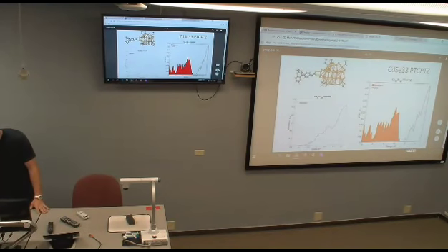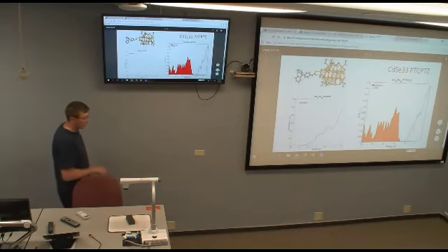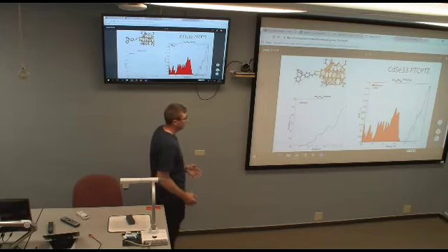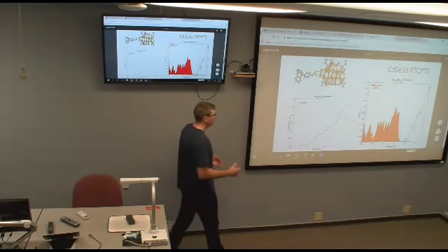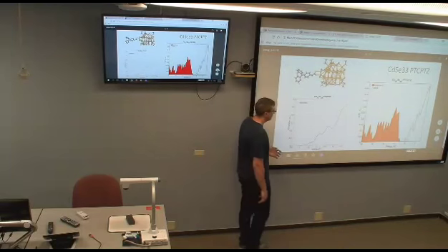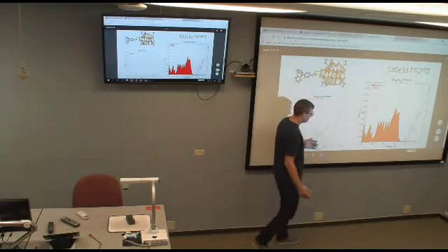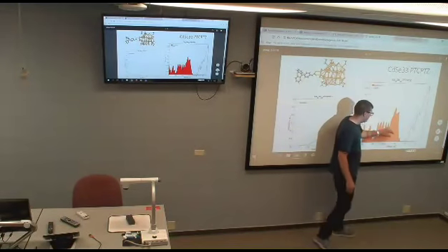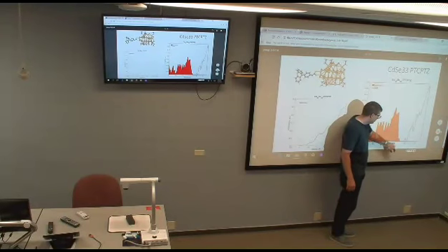And so in comparing this model with now this PTC model, there's a couple different things. The first thing is now the valence band edge is shifted just a little bit. Instead of having a clean break at the valence band edge, there's a little bit more density extruding towards the band gap.